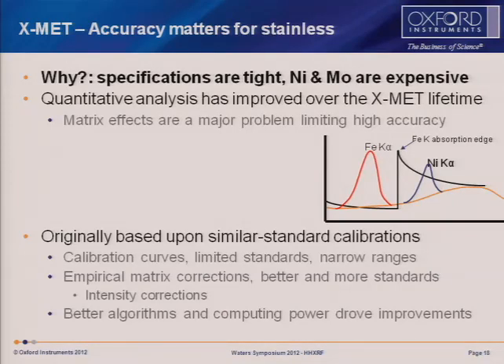And in particular, the intensity corrections, first brought out by John Lucas Tooth and Brian Price in the UK and published in Metallurgia around 1962, gave us equations which allowed us to relate these changing intensities from the spectrum to factors which allowed us to correct for those interelement effects. And now, not only could we get high precision, but with good corrections, we could actually extend the analytical range, reduce the number of standards, and get much better performance out of the instrument. Those went into most of these early systems.